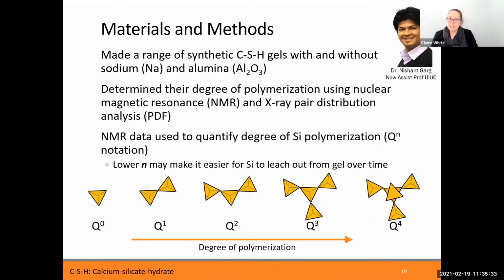So this is an experimental study that we did. We made a whole range of synthetic gels with and without sodium and alumina in there. And we went to quite high amounts of sodium, beyond what people have looked at in the past. We wanted to look at the connectivity of the silicates in the gels to get a sense of how sodium, especially, affects this connectivity. And we used both nuclear magnetic resonance, and X-ray pair distribution function analysis. We found some interesting results there.